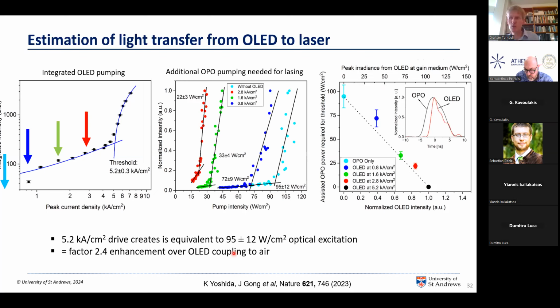And so that's 2.4 times higher than what we can emit from the OLED into air, but that's in good agreement with our calculations of the enhancement you get by tightly integrating the electroluminescent layer and the gain layer together.